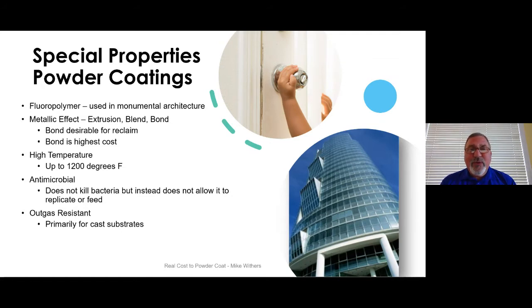Metallic effect, there's 3 ways to produce metallic effect products. Extrusion is the first, where we put everything into the same hopper at the start, and it goes through the extruder, which is how we make powder. The extrusion process, however, is pretty aggressive to the pigment, and so it kind of beats the pigment up slightly, and you don't get as desirable a metallic effect. A dry blend is another way that can be done.